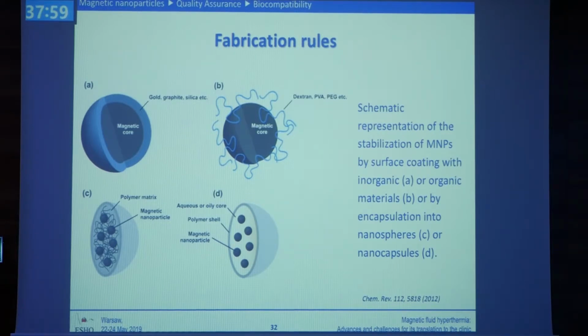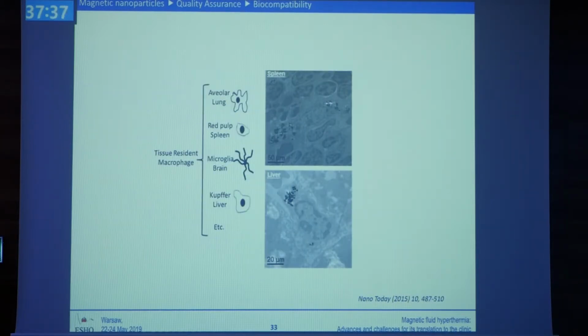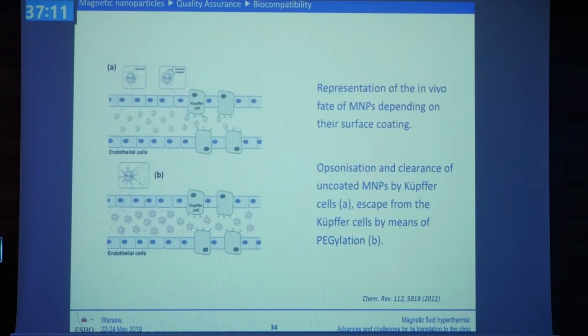By functionalization, I mean that we put around the nanoparticles several different molecules, macromolecules like dextran, they are pegylated and so on, and this gives them a different biological function than the naked magnetic core, the naked nanoparticle. When they have this functionalized layer around them, they can interact with the cells in a different way, because when you have naked nanoparticles inside your body, they will be removed by macrophages that are almost everywhere in your body, and especially in the liver with the Kupffer cells. What happens is that the naked nanoparticles get coated by proteins that are recognized by the Kupffer cells and they are removed from the bloodstream. This process of coating the nanoparticles with proteins is called opsonization.